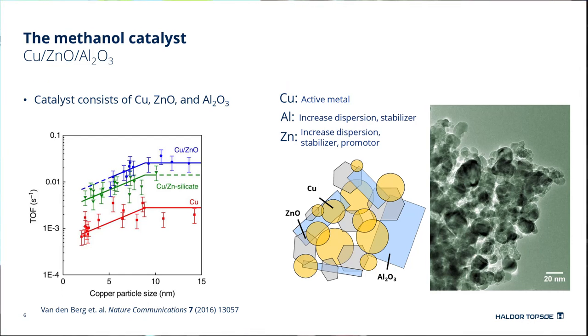And again, zinc is increasing the dispersion of your copper even further, maximizing the area. It's also acting as a stabilizer during operation, but then it has this promoting effect. So by adding zinc oxide to the system, you significantly boost the methanol activity.